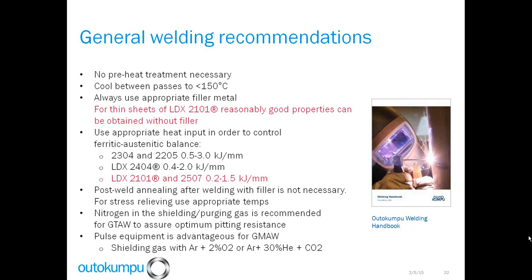Nitrogen in the shielding gas as well as the backing or purging gas is strongly recommended for GTAW or TIG welding. For duplex stainless steel, nitrogen is an important alloying element, and we tend to lose that when we use this welding technique. So we need to use some nitrogen in both the backing and shielding gas if possible. When we're using GMAW, pulsing is advantageous, and some of the typical shielding gases are argon with 2% oxygen, argon with 3% CO2, as well as argon, helium, CO2 trimix gases.